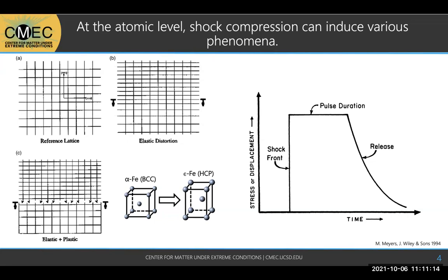But so for shock, if you compress further in some materials, you have phase changes also. At this point, you've distorted that lattice so much that the atoms actually shift into an entirely different configuration. What I'm showing there is just an example transformation in iron from a BCC lattice to an HCP lattice. And so you can see how that perfect cube ends up getting squished a little bit and elongated.